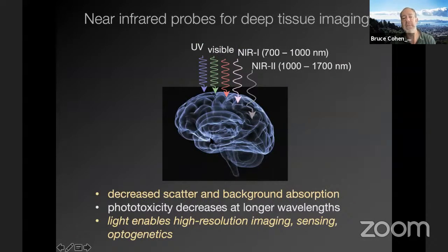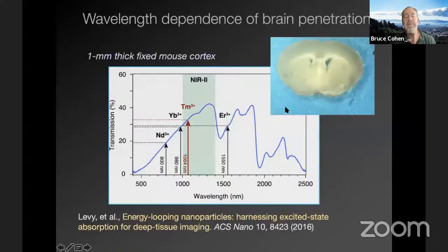One of the things that really drove us, particularly for these materials, is that near infrared light will penetrate tissue in ways that ultraviolet, and even visible light, will not. This is simply a matter of scattering, which is largely wavelength dependent, and also the fact that there are very few things in cells that absorb at these wavelengths. So this is a piece of fixed mouse brain, and my collaborator, Emery Chen, took an absorbance or transmission spectrum of this and showed that when you get into the near infrared 2, between 1,000 and 1,400, you have maximal transparency.